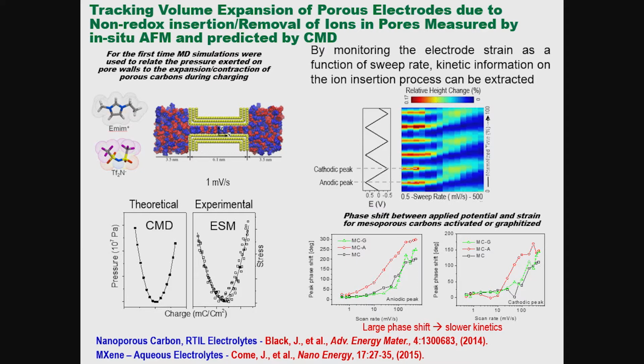I don't have time to go into the details of this, but we're predicting the pressure exerted by the electrolyte on the pore walls as a function of charge state. We can measure that by electrochemical strain microscopy, through the expansion and contraction of the nanoporous electrode in contact with the electrolyte, and get very nice agreement. We can also vary that strain measurement as a function of voltage sweep rate, and this deviation gives an indication of the transport dynamics, the ability of the electrolyte to go into or come out of the interface.